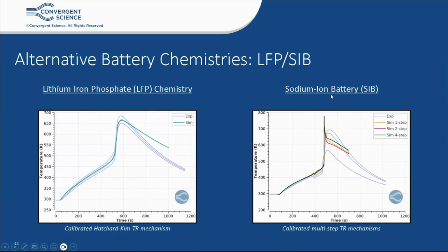We also received data for a relatively new battery chemistry, sodium-ion batteries. For the sodium-ion batteries, there were some uncertainties on the battery properties. We were not fully confident that we had the correct battery properties, but we were still able to get well-calibrated multi-step thermal runaway mechanisms for SIB data. And just to show the versatility of this calibration approach, we were able to calibrate a four-step, a two-step, and even a one-step thermal runaway mechanism to experimental data.